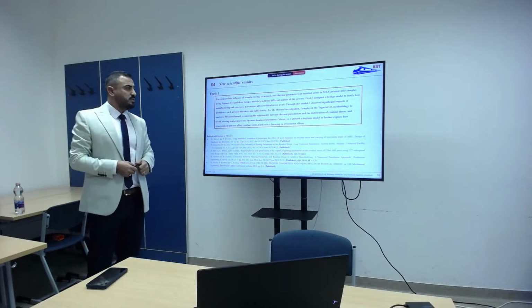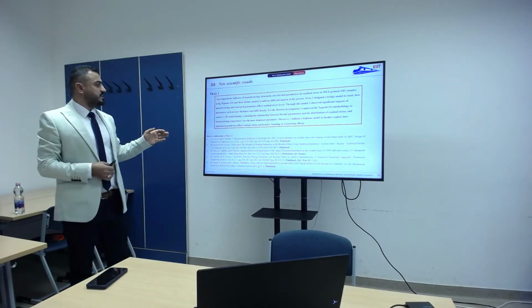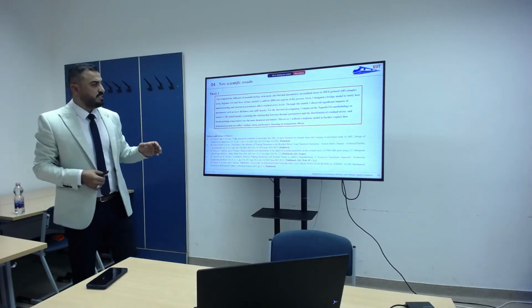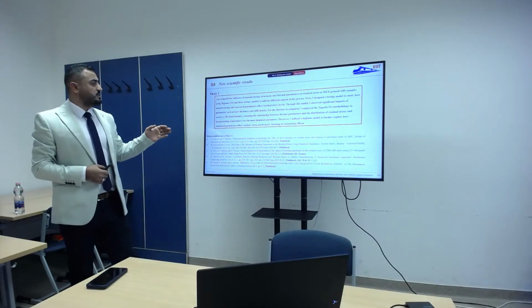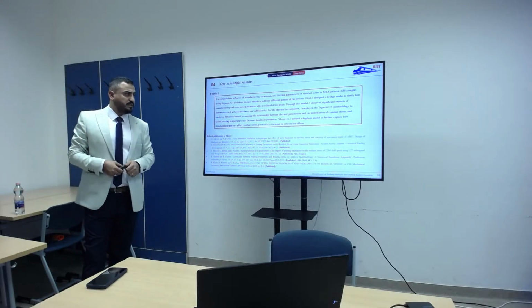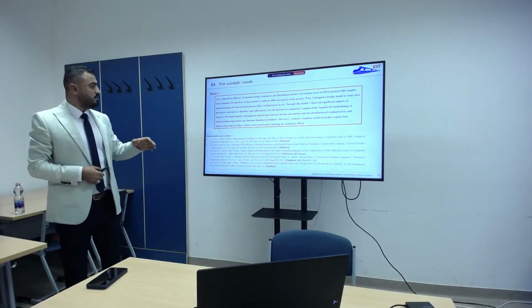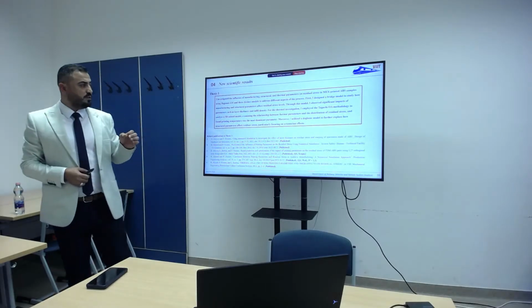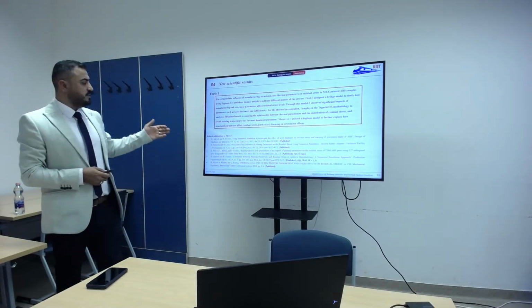For the thermal investigation, I employed the Taguchi orthogonal array methodology to analyze a 3D component model, examining the relationship between thermal parameters and distribution of residual stress, and found printing temperature was the most dominant parameter. Moreover, I utilized the dog-bone model to further explore how structural parameters affect residual stress, particularly focusing on the orientation effect. And here is the list of publications related to thesis number 1.